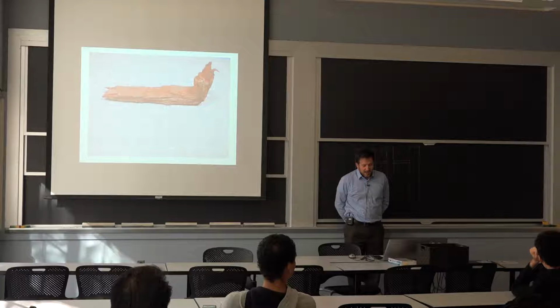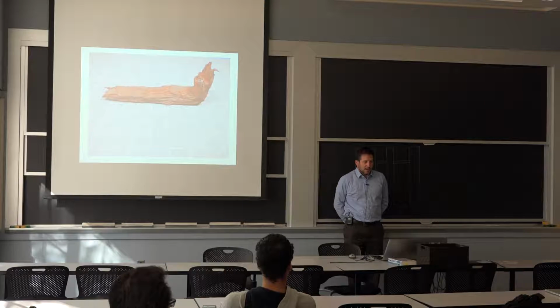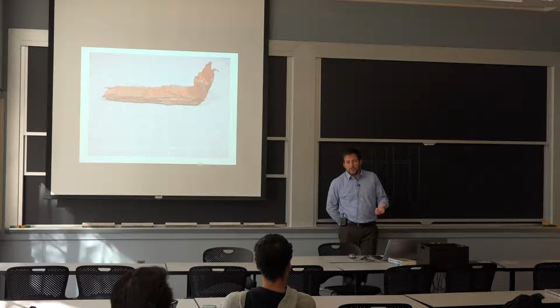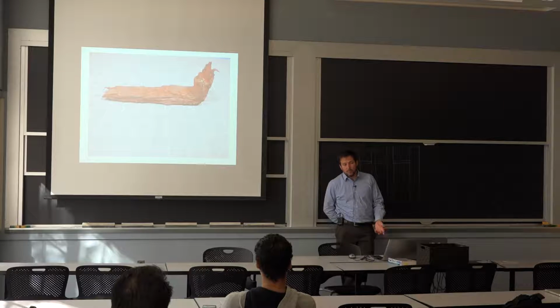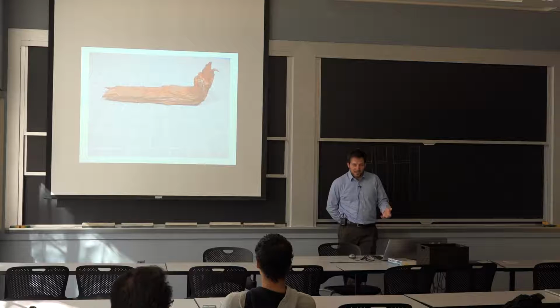So it is not very solid. It looks solid, but it's not a solid metal. The density of the deposit is about 20% the density of steel. So the amount of material lost in this case is only 1 or 2 millimeters as opposed to 10. So there wasn't any problem.